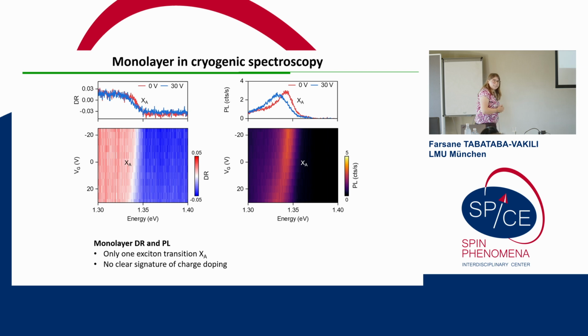So let's start with the monolayer. Another thing that I find quite curious about this material, in contrast to transition metal dichalcogenides, where it becomes interesting in the monolayer, is that here the monolayer is kind of boring from an optical point of view. So let's look at the differential reflectance and the photoluminescence. Here we observe one weak excitonic feature, which we call XA.